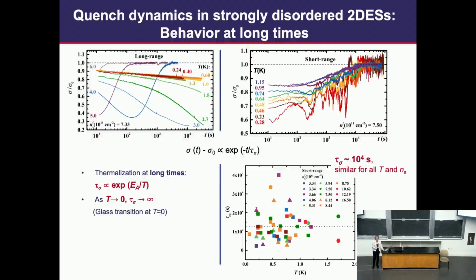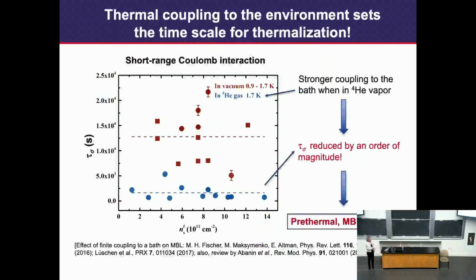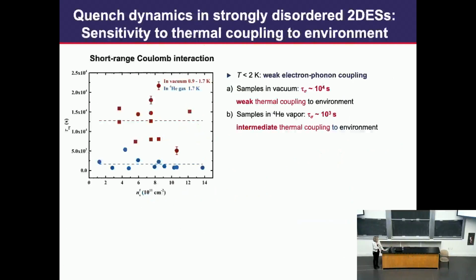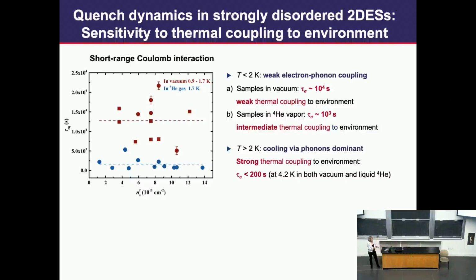So we repeated some of our measurements with the sample not in vacuum, but in helium vapor, and saw that the equilibration time is reduced by an order of magnitude — exactly what you'd expect in the MBL case. These measurements were done at temperatures below about 2 Kelvin, where electron-phonon coupling is negligible. We also repeated measurements at higher temperatures where coupling to phonons dominates, and found the thermalization time reduced by at least another order of magnitude. It didn't really matter where the sample was placed, because all the heat transfer is dominated by phonons.